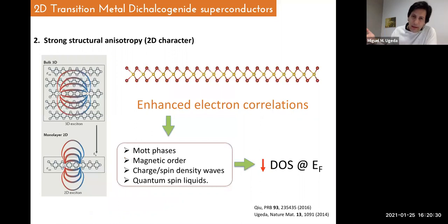Okay. So obviously this family of materials is almost purely two-dimensional, because superconductivity is basically sustained along the transition metal element. The chalcogen does not play a large role for superconductivity at all. So basically in two dimensions, the charge screening gets reduced due to the change in the environment. That's what I wanted to highlight here. And therefore, lower screening enhances electron correlations. That's why, in general, some of these phases show up in this two-dimensional limit or are even stronger than in bulk, right?